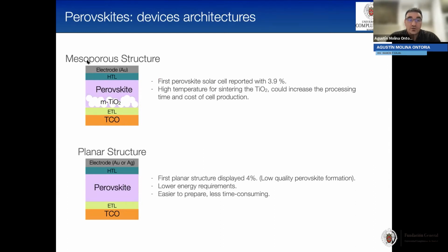The first one is called the mesoporous structure. This structure mainly comes from dye-sensitized solar cells, in which we use a transparent conductive oxide. On top of that, we deposit an electron transporting layer, typically another planar layer of titanium oxide. On top of the titanium oxide, we deposit mesoporous titanium oxide. Then the perovskite infiltrates the pores of this mesoporous titanium oxide. We use the hole transporting material, and finally we thermally deposit the electrode.